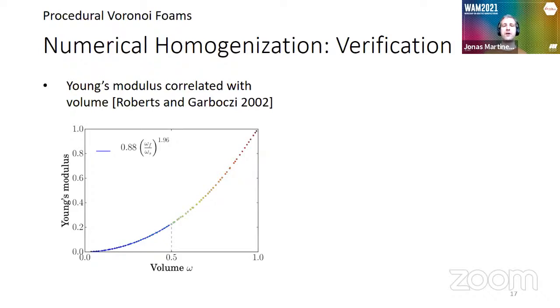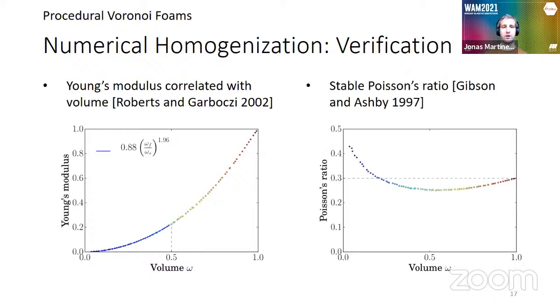Voronoi diagrams have basically this kind of behavior where the relative volume is correlated with the Young modulus following some kind of power law. And also the Poisson's ratio remains fairly stable, along with the Poisson's ratio of the solid material.